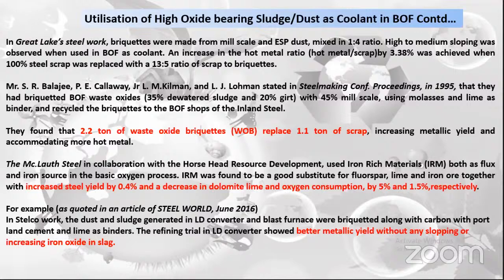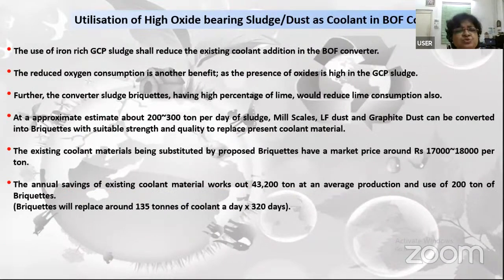These are the benefits. The use of iron-rich GCP sludge will reduce the existing coolant addition in the BOF converter. One by one, you will be able to find out in which way this recovered item will be giving us benefit, how we are going to derive wealth from waste. The reduced oxygen consumption is another benefit, as the presence of oxide is high in the GCP sludge. Further, the converter sludge briquettes having a high percentage of lime would reduce the lime consumption also. At an approximate estimate, about 200 to 300 ton per day of sludge, mill scale, LF dust, and graphite dust can be converted into briquette with suitable strength and quality to replace present coolant material.